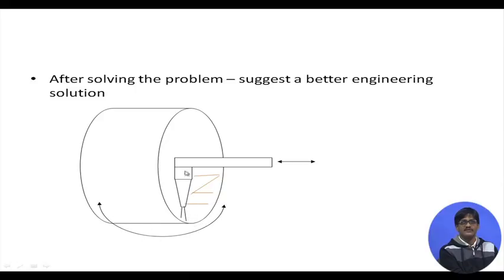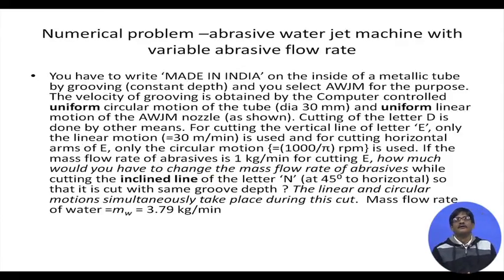What's the diameter of this tube? 30 millimeters. Okay. What's the speed of this particular nozzle? 30 meters per minute. And what is the rotational speed? It's a constant rotational speed, either on or off. Let's read it up. Yes, the velocity of grooving is obtained by the computer controlled uniform circular motion of the tube whose diameter is 30 millimeters and uniform linear motion of the abrasive water jet nozzle as shown. What's that uniform linear motion? It is 30 meters per minute, mentioned later.